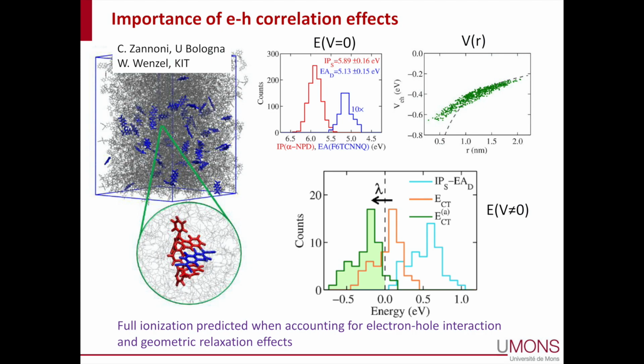So if you look at the distribution here, these are the CT energies, ignoring electron-hole interaction. They are all on the positive side, no doping. If you account for the electron-hole interaction, if you account for the reorganization energy, you end up with this green distribution that is on the negative side, so this is full doping. You can see that instead of having finite levels, you get a distribution of levels, and this distribution is the disorder that is associated with the amorphous structure of the system and the associated energy distribution that you get in the CT pair energies.